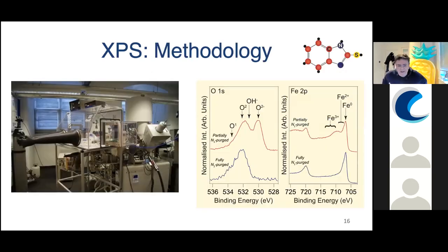Now, a key part of our work is the specifics about the methodology, our approach. So here is the XPS facility at Manchester that we typically use. It's a Kratos XPS facility. And the key thing for our work is this glove box that's attached here. For our experiments, this is filled with nitrogen. And what we do is we remove the sample out of the inhibited solution into this nitrogen-filled glove box, so it's not exposed to the laboratory air.